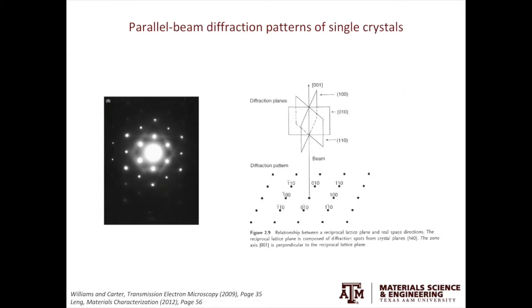Starting from single crystals: because the wavelength of the electron beam is very small, to satisfy Bragg's law the angle theta is very small. This means that when the lattice planes are more or less parallel to the electron beam, they will undergo Bragg diffraction. Using the 1-1-0 set of planes as an example, it gives rise to the 1-1-0 spot. The G vector drawn from the direct beam to the diffracted beam is the plane normal — in general, any G vector in the diffraction pattern is the plane normal of that set of planes.